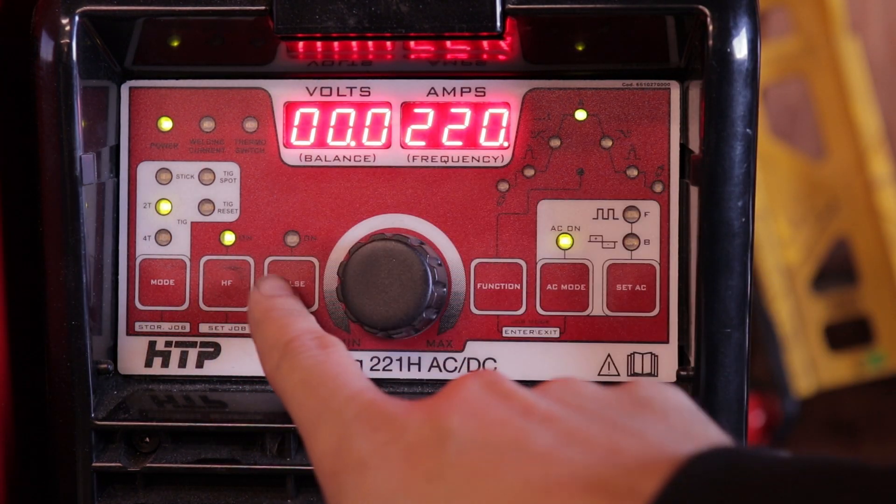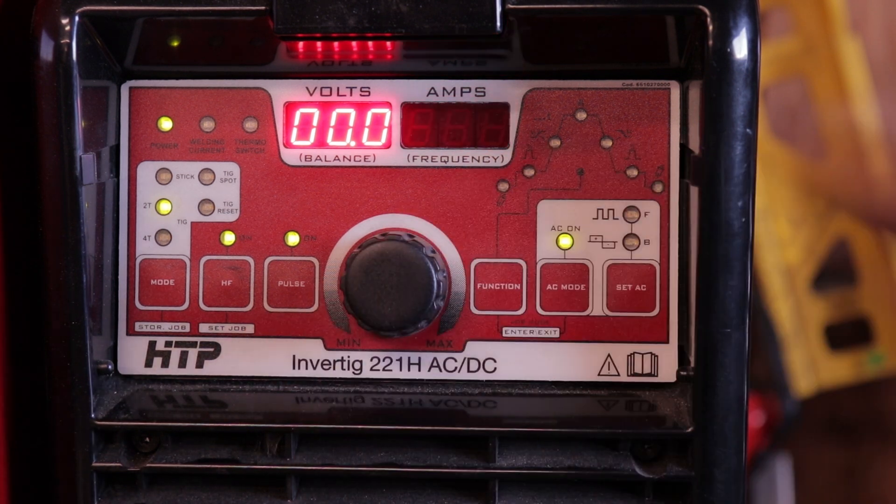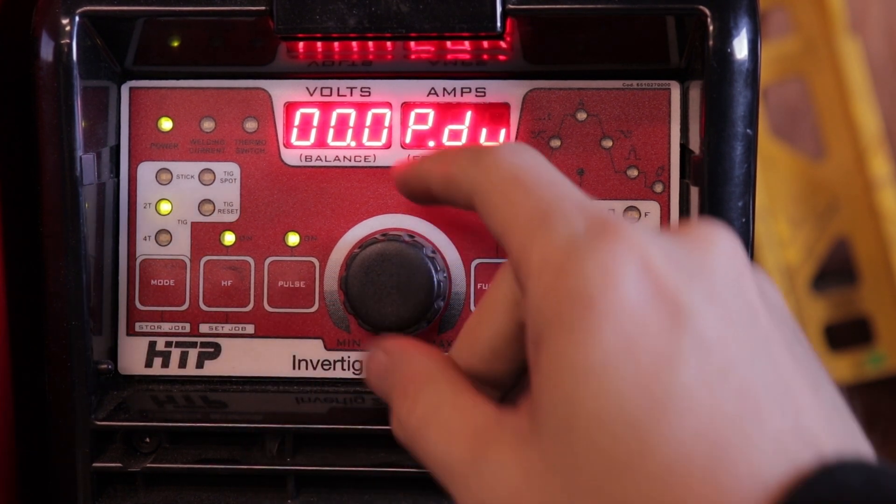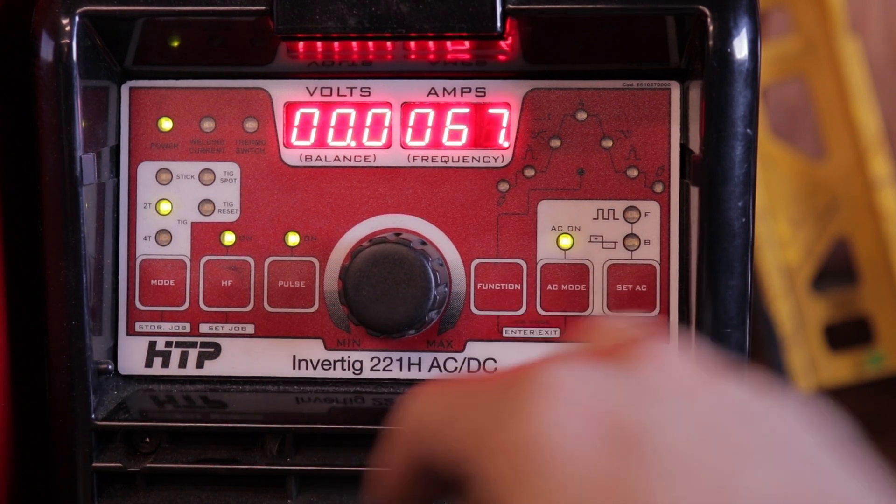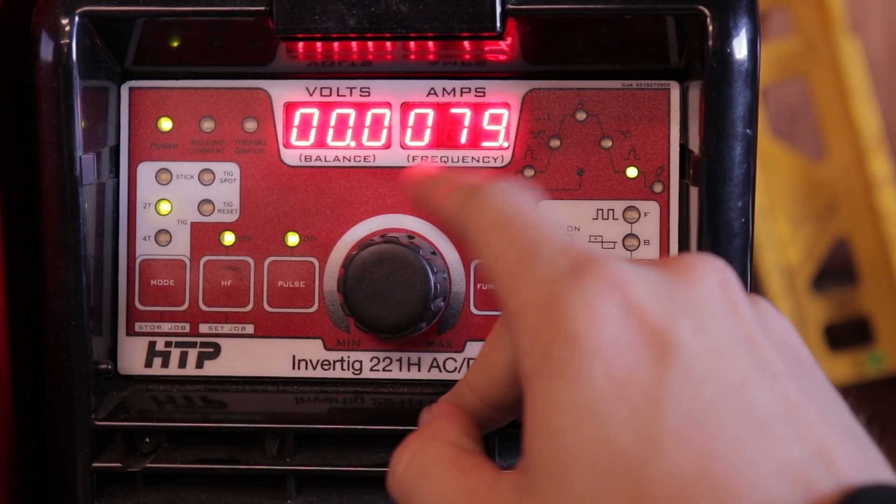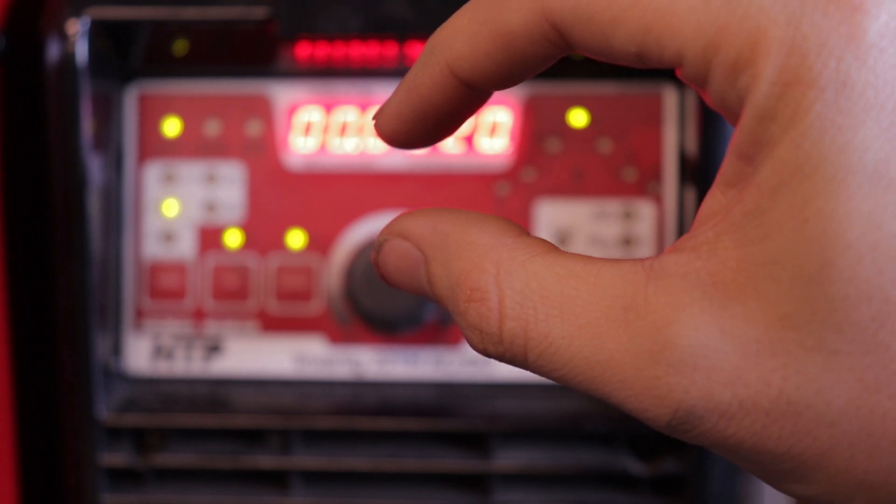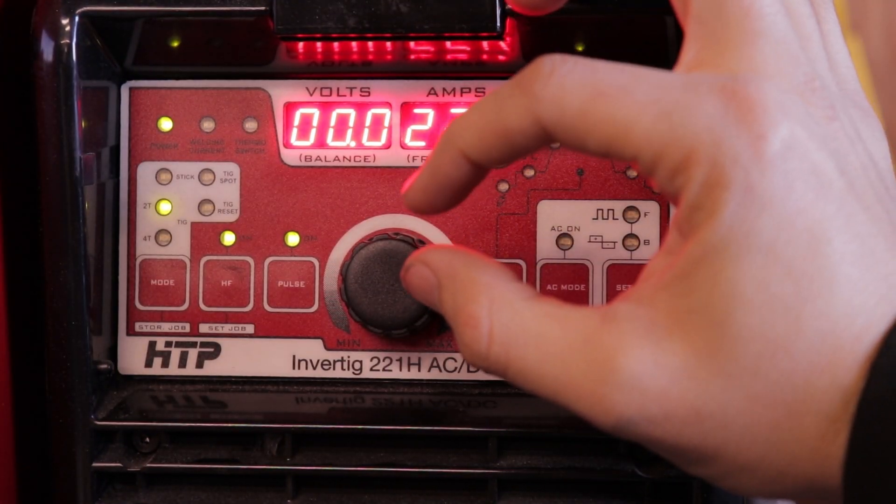Now, I also want to throw on some pulse with it. So, my pulse frequency, I want it around one pulse per second so that I have enough time to add my filler. We'll keep this one up around 67. And then put this one up at 70. And basically what that's doing is it allows when you're pulsing for the puddle not to quench all the way. Say this right here is when it's full amperage. And then when the background hits, it only hits for about 30% of the time. So, then it narrows up to about here. And for only 30% of the time, it's like that. So, it's 70% of the amount of total amps you get. So, it narrows up just a tiny bit and it just barely stays like that until it hits full amperage again.